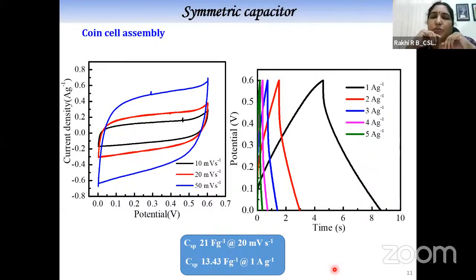Now, what happened in the real device? We made the electrode material by the exfoliation method, and we fabricated the supercapacitors, and these are the supercapacitor measurements which we have got. These are the CV measurements and CD measurements. We can see that these are not completely rectangular, but quasi-rectangular, and similarly, the GCD curve is not completely triangular. From the GCD and CV curves, Csp values were calculated as 21 farad per gram and 13 farad per gram, but we should report only 13 farad per gram because the capacitance value calculated at 1 ampere per gram is the only one we should use for reporting.